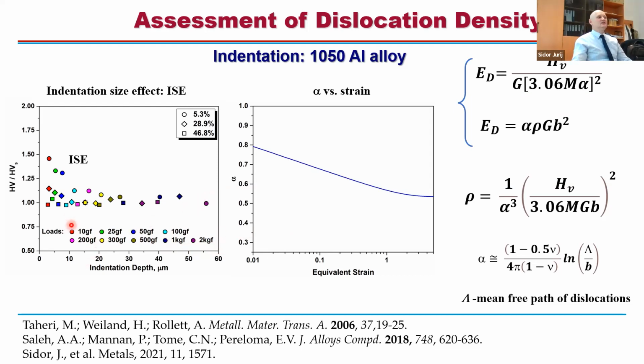So when you do this, you have to be aware that there is a so-called indentation size effect, where the hardness, in the present case the Vickers hardness, is overestimated at lower loads. And then when you have the information about the hardness, you always select data from the saturation zone in order to avoid this overestimation. So the group of Tony Rollett and also other groups developed a technique to estimate the stored energy based on the Vickers hardness.